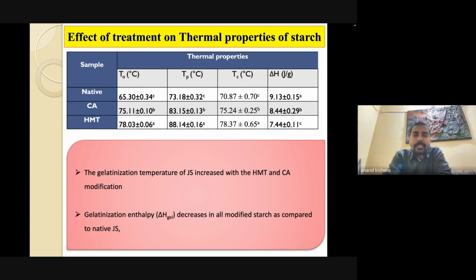If you look at the effect of treatment on the thermal properties of the starch, you can see the transition temperature increases after modification with citric acid and HMT. The gelatinization temperature of jicama starch increased with HMT and CA modifications, which indicates a stable configuration and better thermal stability for further processing. The gelatinization enthalpy decreases in all modified starch. However, with citric acid it is higher compared to the HMT starch. The reason may be that citric acid does cross-linking and strengthens the amylose and amylopectin arrangements.